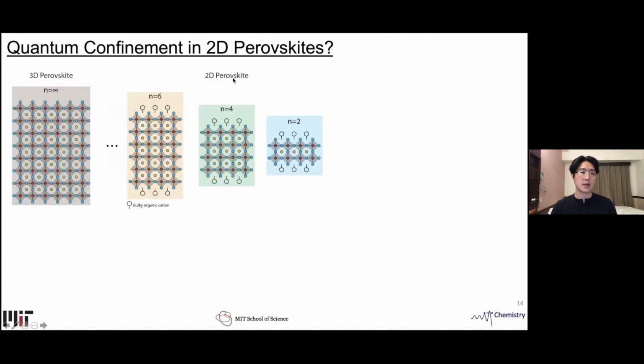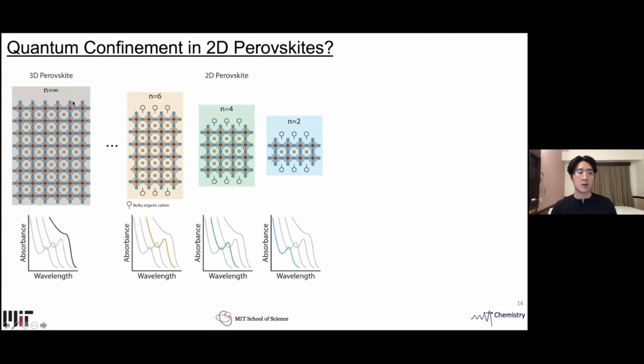Then what is a 2D perovskite? Compared to the 3D perovskite, which has an extended, infinitely long network, the 2D perovskites are formed by having a layer of bulky organic cations between sheets of perovskite layers. Going from an n value of infinity, where n is the number of octahedral layers between the organic cations, going from a high value to a low value, we see an increase in the band gap, noted by this blue shift in the absorbance profile.